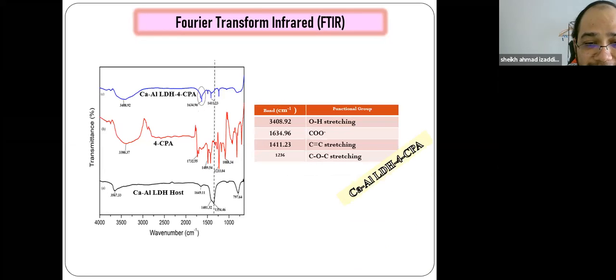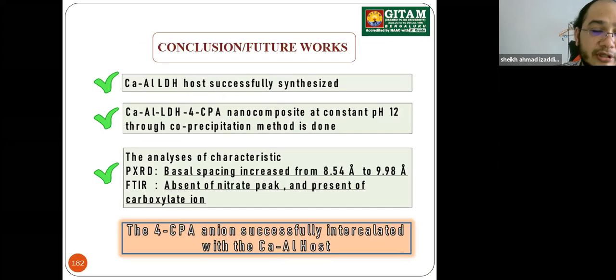So in conclusion, we could conclude that the calcium aluminum LDH was successfully synthesized. The calcium aluminum LDH 4-CPA nanocomposite at constant pH 12 has been made through the co-precipitation method. From the PXRD analysis, the basal spacing has increased from 8.54 Angstrom to 9.98 Angstrom. For the FTIR, it is obviously seen that the nitrate peak is absent and the carboxylate ion is present, which represents the 4-CPA anion.